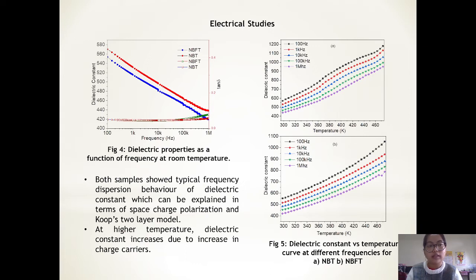Also, we can see that the iron-doped sample has a lower dielectric constant as compared to the pure NBT, which may be due to the lower polarizability of the Fe3+ ions substituted in place of the Ti4+ ions.